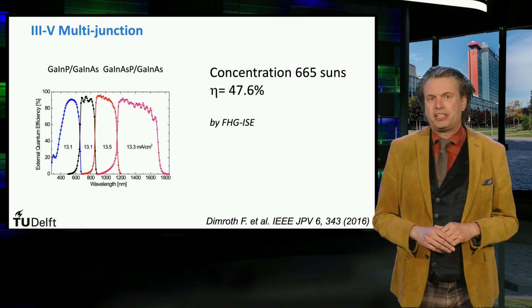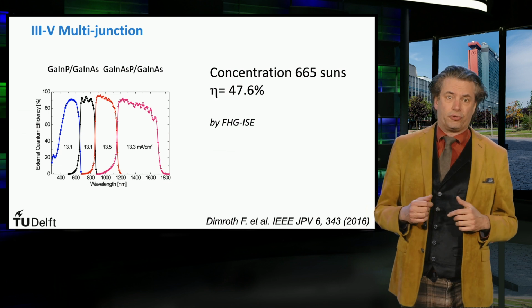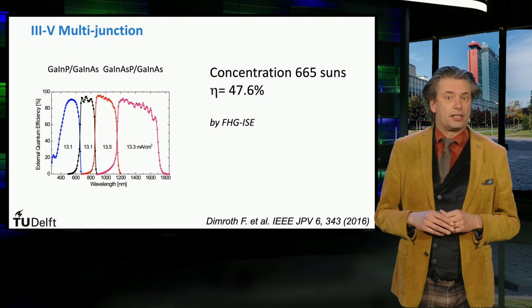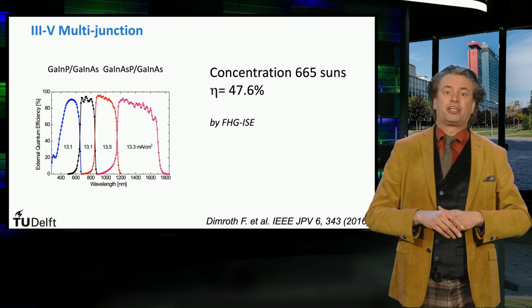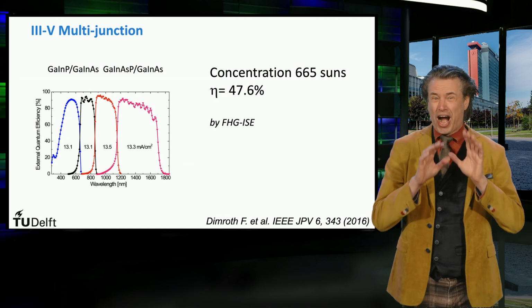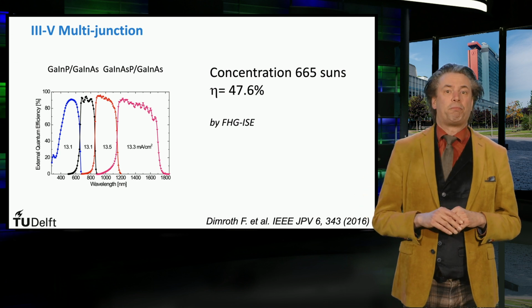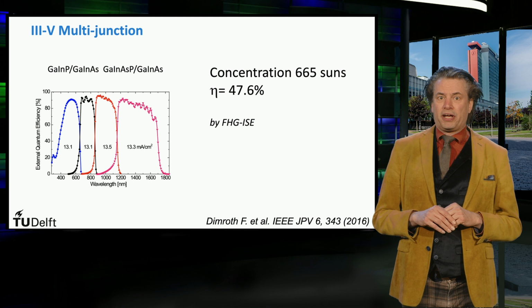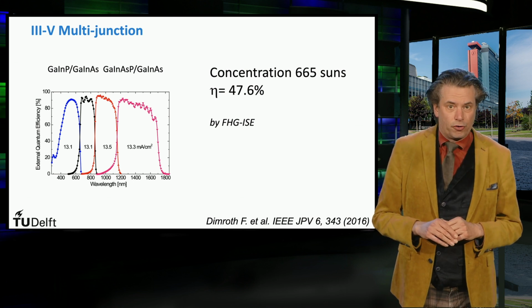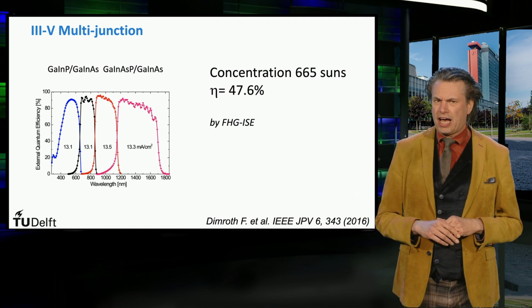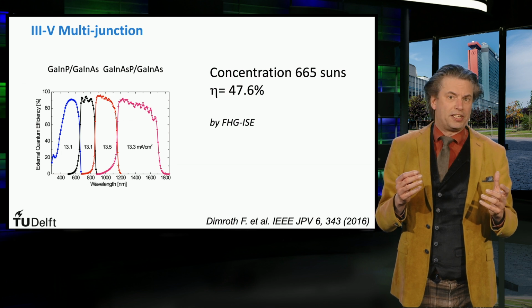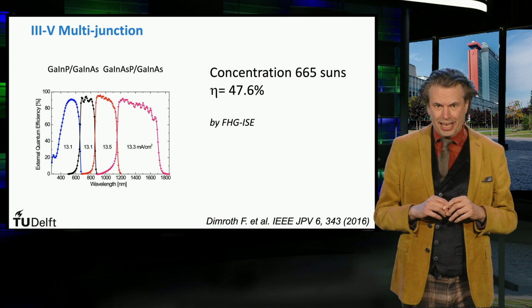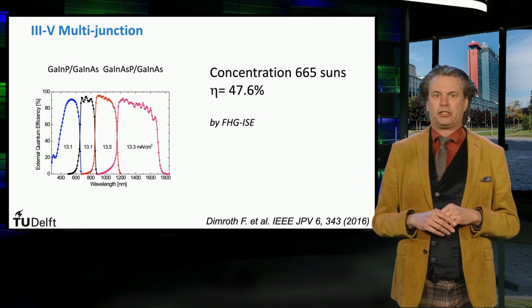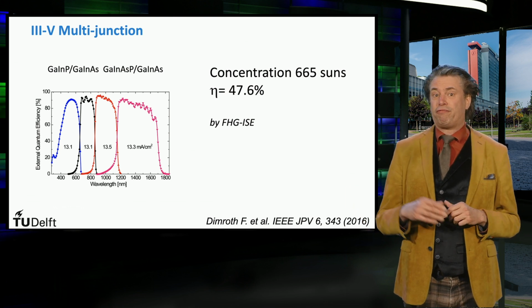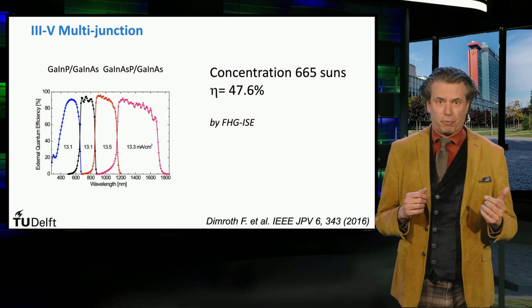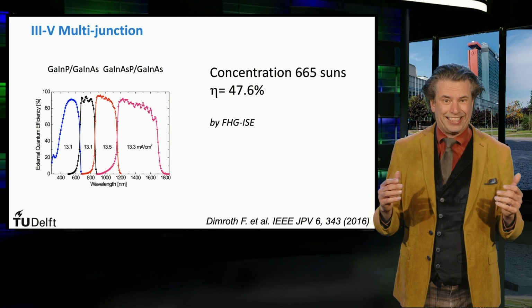If we consider the III-V technology, we see that under concentration, the 4-junction bonded device architecture based on gallium indium phosphide, gallium indium arsenide, gallium indium arsenide phosphide and gallium indium arsenide has resulted in the highest efficiency reported for any PV device in the world, which is 47.6%. This was accomplished by a collaboration between Soitec, CEA and Fraunhofer ISE. Note that Alta Devices has achieved a record conversion efficiency of 29.1% for a thin film single junction gallium arsenide PV cell of about 1 square centimeter. Boeing Spectrolab has demonstrated a 5-junction bonded cell with an efficiency of 38.8% at the 1000 watts per square meter standard test conditions.